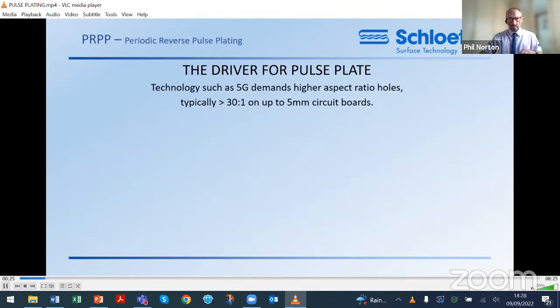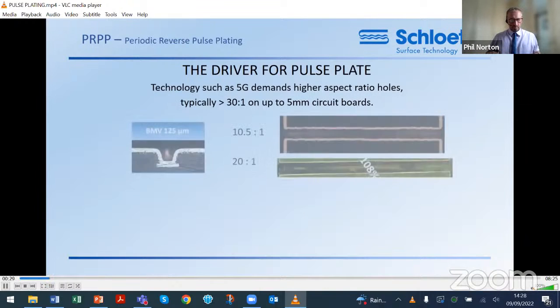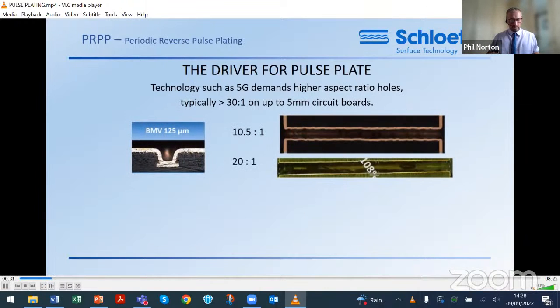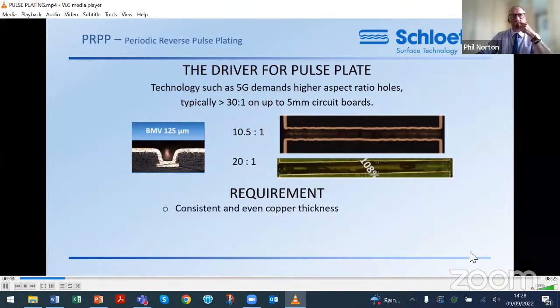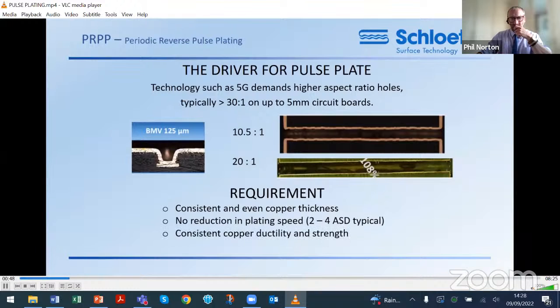Technology such as 5G places high demands on circuit complexity, commonly requiring plating in 5mm boards with 30:1 aspect ratio holes. Aspect ratios of 10 or 20:1 are commonplace. But we still require consistent copper thickness, good plating speed, consistent physical properties of the plated deposit, and, importantly, a process which is easy to control and maintain.